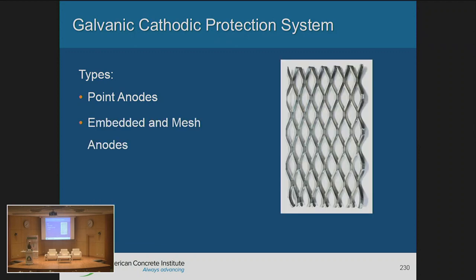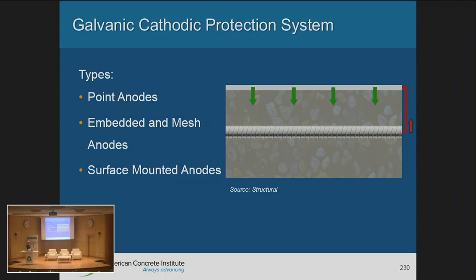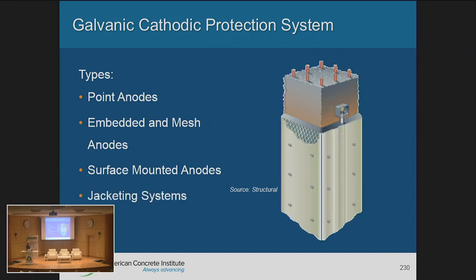We have the embedded mesh anode, where you embed it within the concrete, and it provides continuous energy. You have the surface mounted, where you melt a metallic element and press it on top of the surface, connect it to the bar, and then it provides energy. That could be maintained up to 10 years. Once that is depleted, you can reapply it again.